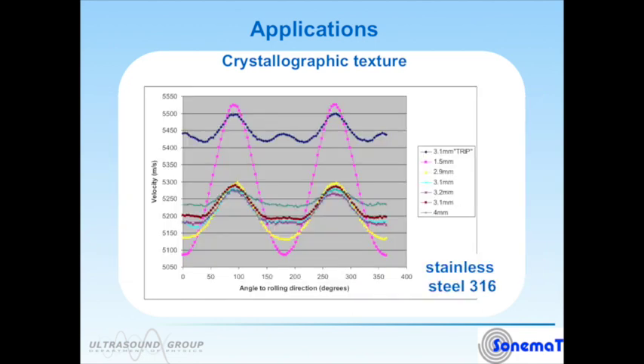This is an example of measuring the ultrasonic velocity and how it varies with rolling direction for some metal sheets. In this case, the top dark blue trace, just for comparison, corresponds to a 3.1mm thick TRIP steel alloy. You can see it looks very different to the other plots shown here, and the other plots shown here on the lower bunch of graphs, well, they all correspond to a 316 stainless steel that's been progressively rolled to different thicknesses. You can see as the steel is rolled how the anisotropy develops.